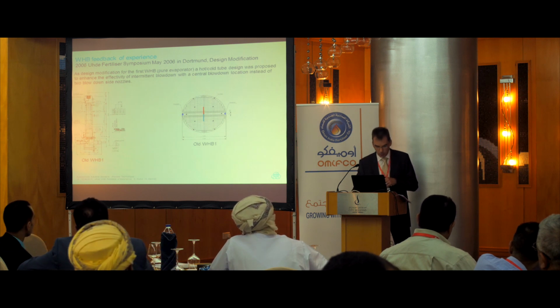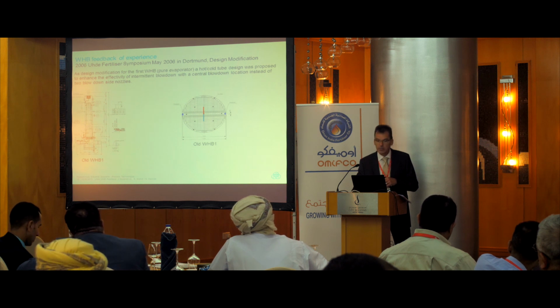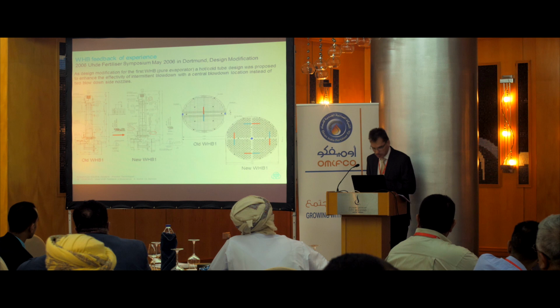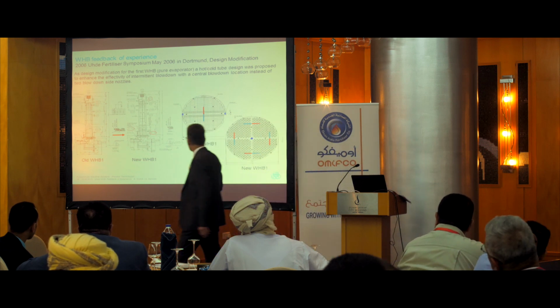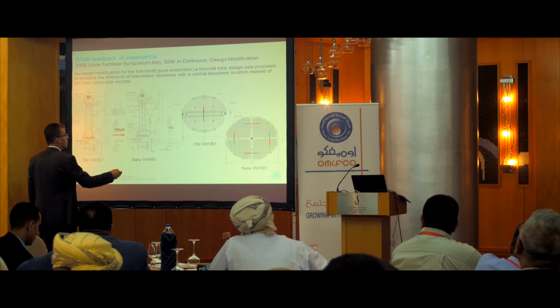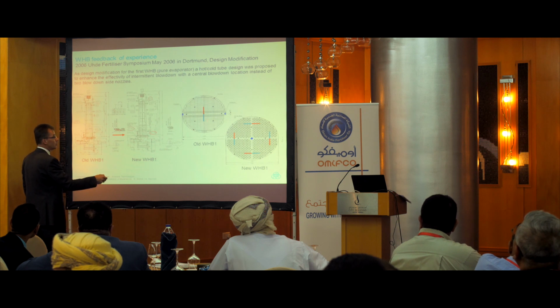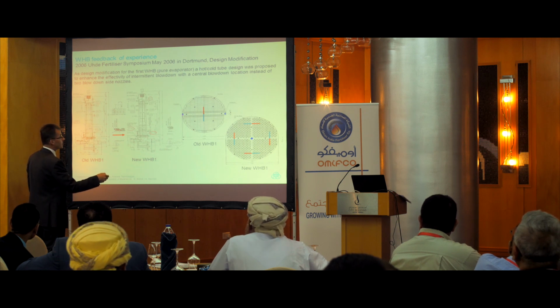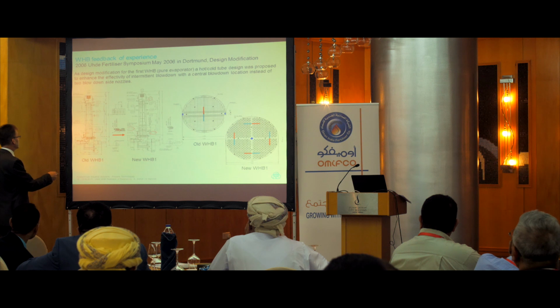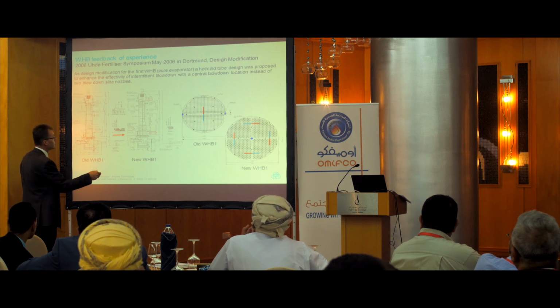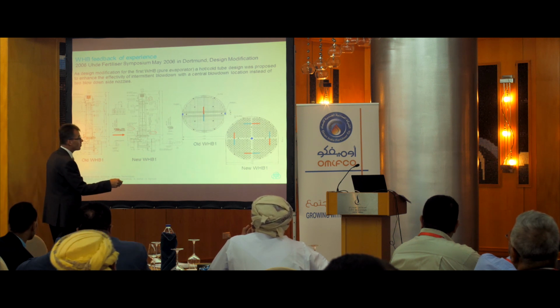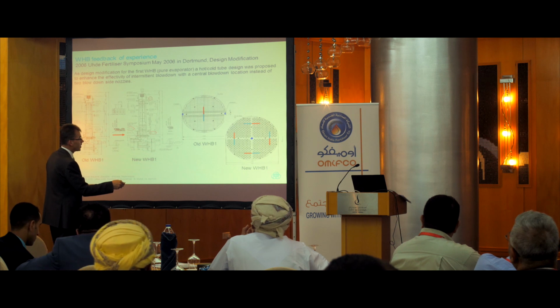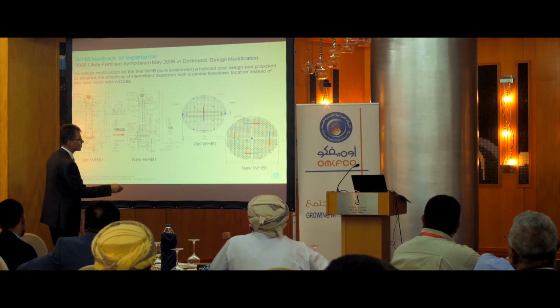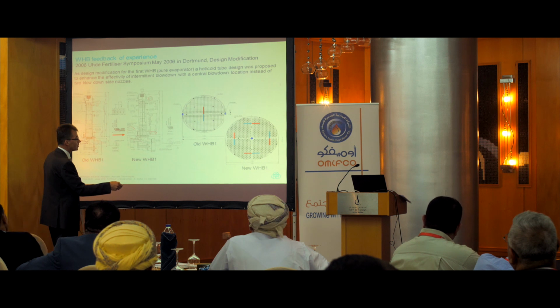Therefore, the standard U-tube boiler was converted into a so-called hot-cold tube design. That means the design before, when you look at the tube sheet: hot side, cold side, simple U-tube. Blowdown was located on the side. Here have been the blowdown nozzles in the older plants. We changed this design to a so-called hot-cold segment design. Hot, cold, hot, cold, hot, cold. And we have been able then to put the intermittent blowdown in the waste heat boiler 1 over in the middle.